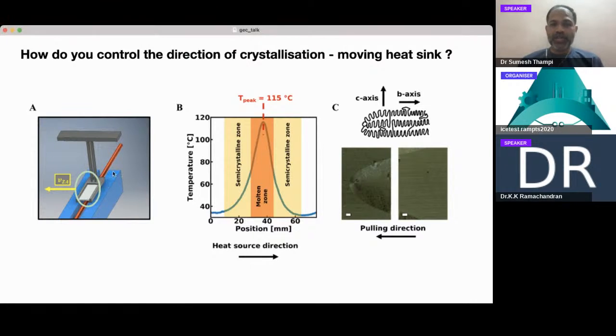So if you think about how the temperature profile would be, at the top it gets heated and then it cools once again. That's exactly the temperature profile shown here in this picture, where on the x-axis you have the position measured from the top to the bottom, and on the y-axis is the temperature, and you can see that the temperature increases, reaches a maximum and goes down. Wherever there is this maximum, that corresponds to the melt phase, and on either side you will have the cool phases. And what was observed was that when you do this heating and then pull this heating element, very interesting structures form.